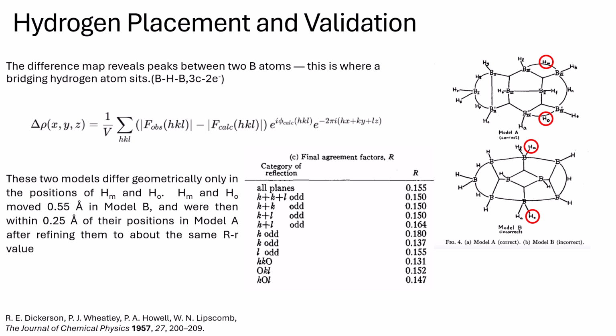In addition to that, he also did a refinement of these two models, and he found that HM and HO moved 0.55 in Model B, and in Model A they only moved 0.25. And overall, the final agreement factor R for all the planes that could be obtained in the molecule is still lower for Model A than Model B. So he reached the conclusion that Model A is the actual structure of B9H15.